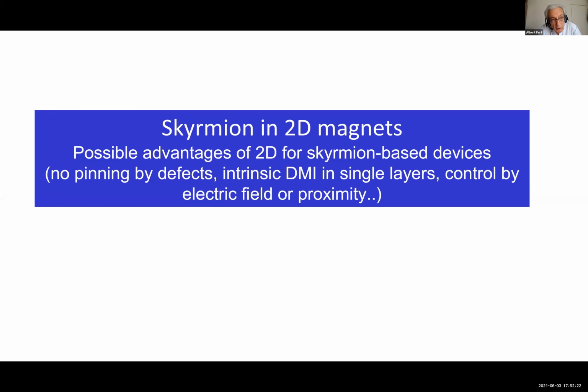And in fact, the advance has been very fast during the last five years. One knows how to stabilize skyrmions in a thin layer of cobalt, for example, in multilayers, for example cobalt platinum prepared by sputtering. One knows how to generate skyrmions by current pulses. One knows also how to detect the skyrmions, either by MFM images or simply by anomalous Hall effect, by electrical measurements. And one knows a lot about the current induced motion of skyrmions. Large velocities, larger than 100 meters per second, can be obtained by pushing with current through the spin orbit torques.